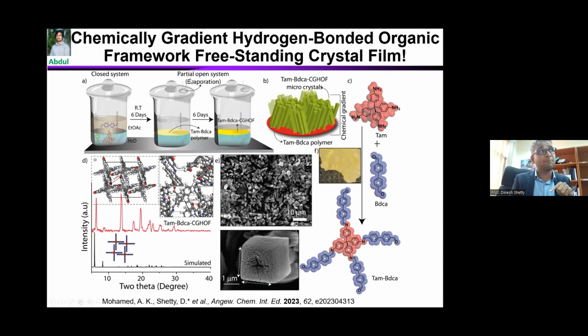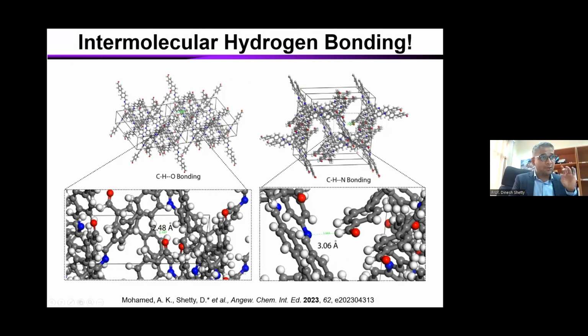But once we do the partial open system, slowly the hydrogen bonded frameworks made of oligomeric COFs come and self-assemble on this, and due to the strong hydrogen bonding, they stay on the surface of this COF film. So the beauty of this work is you can easily convert the chemical gradient into a different form of framework formation here. In one case, an amorphous film, then you have a hydrogen bonding network sticking to that. And then we did all the study to understand what sort of interaction it has, why it is forming, and then